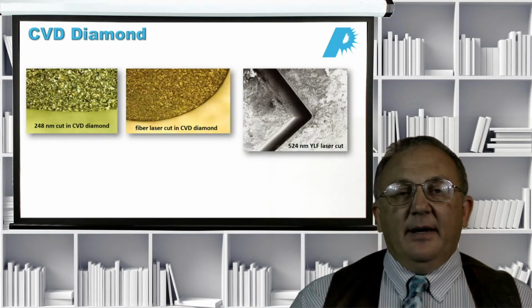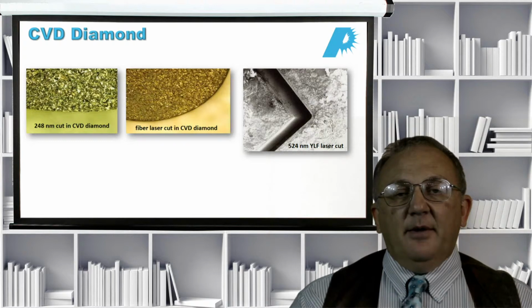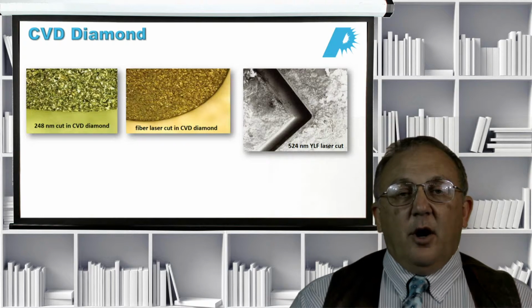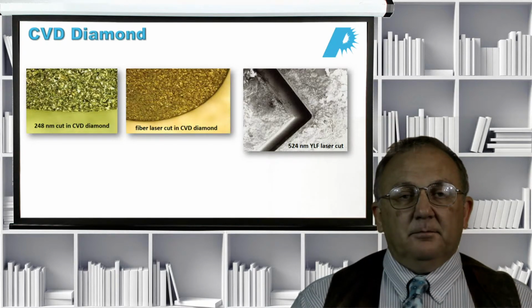On the right-hand side, again, we see another piece of diamond that was cut with a 524 nanometer laser. And basically, this cutting also shows really no signs of carbonization, microcracking, or any negative effects.